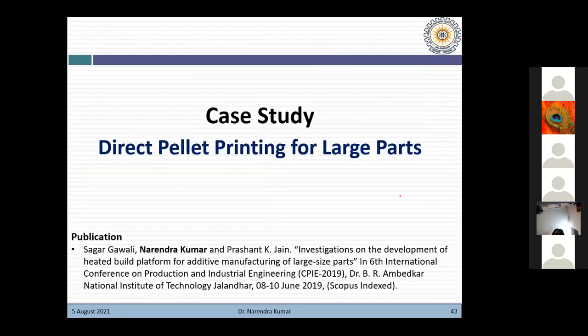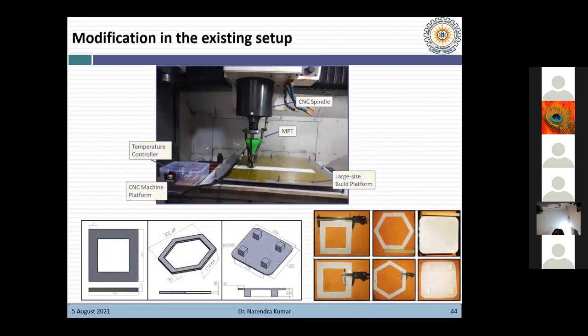Then we also explored our setup for large part fabrication, because this is again a problem. If you look at the available FFF printers, you will find very small size FFF printers. Because we were using a CNC milling machine in our research, we thought we should explore this area also. Large part fabrication was attempted because we wanted to see the feasibility, whether it can be done or not. We increased the nozzle size from 0.4 to 5 mm. Then we attempted some of the shapes.